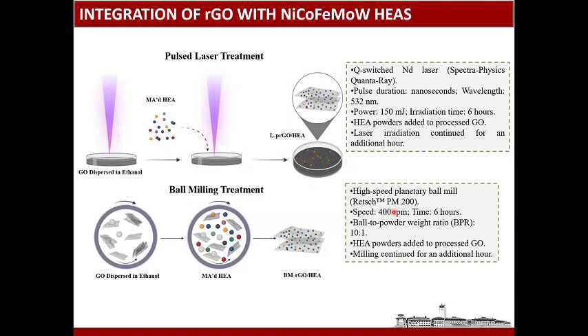And then we introduced reduced graphene oxide to increase the conductivity between the grain boundaries in the high entropy alloys, because the reduced graphene oxide is conductive. It's not as conductive as the graphite, but it is conductive. So in this case we did pulse laser treatment. We used a nanosecond laser. We dispersed graphene oxide in ethanol, and then we added ball milled high entropy alloy nanoparticles into the graphene oxide ethanol solution, and then we did pulse laser deposition.